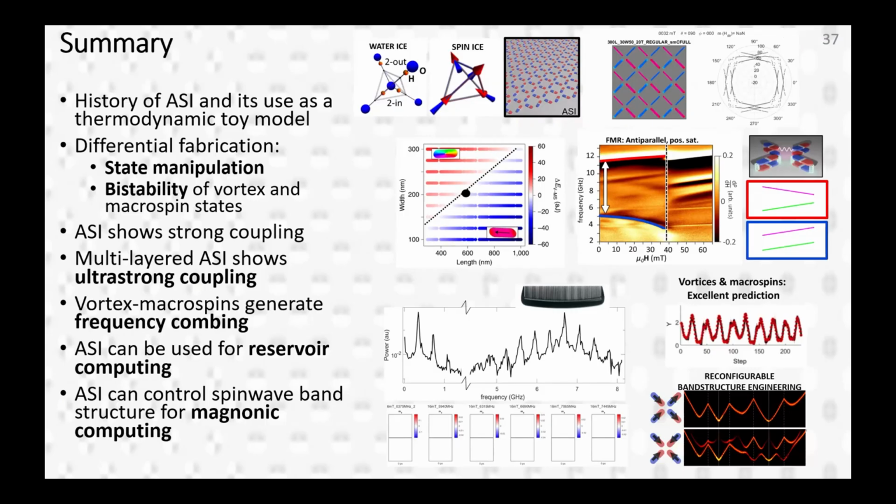Yeah, so it's easy, say, in Kagome spin ice to see where the frustration is, because in Kagome you have this hexagonal structure, and at the vertex you have 2 in, 1 out, or 1 in, 2 out. And there it's very easy to see because you have 2 interactions that are competing with each other. In the case where you have 2 in, 2 out, this square and the pyrochlore, the frustration doesn't happen unless you have a large number of these states. And it's because there are many different ways to arrange them where the energy is the same.